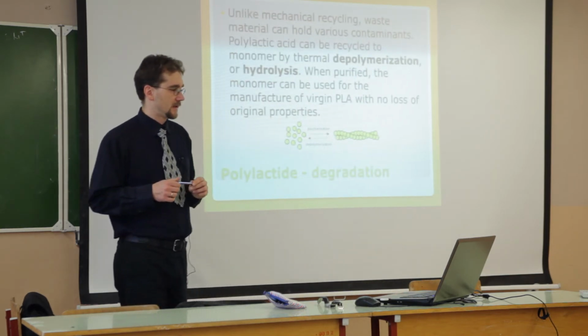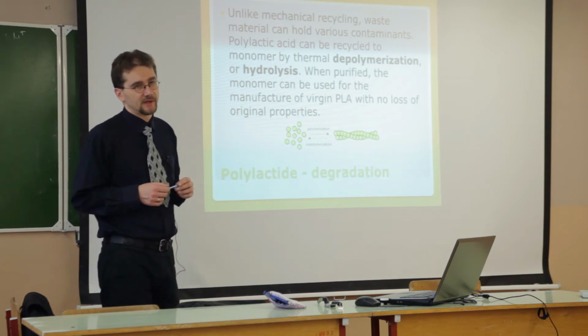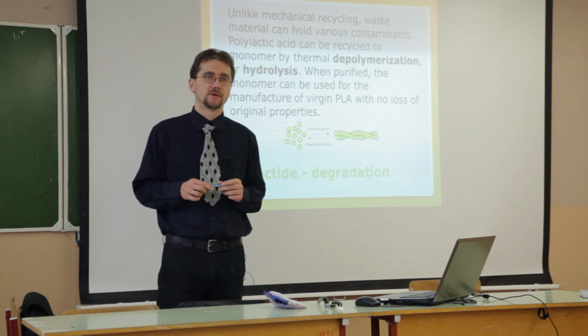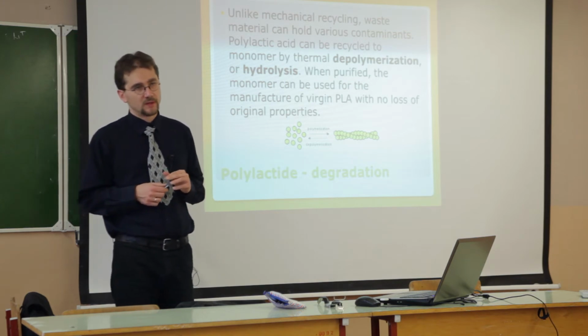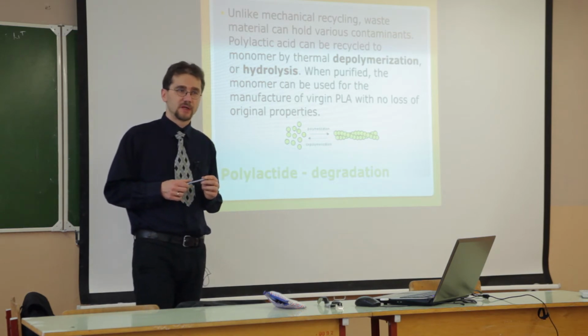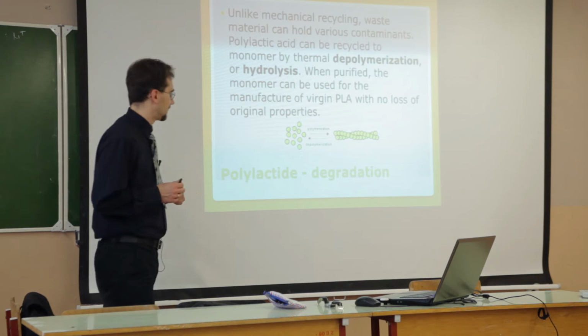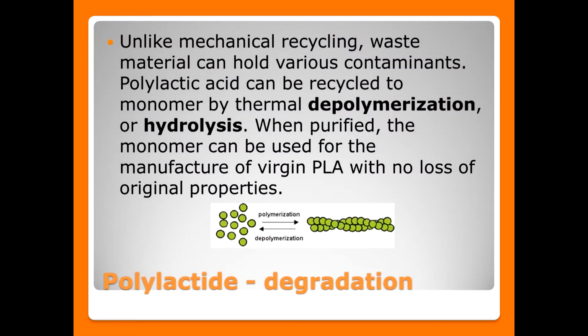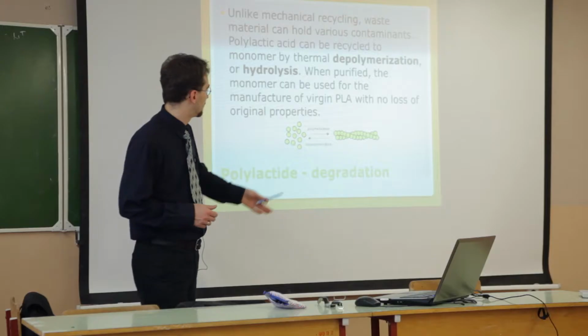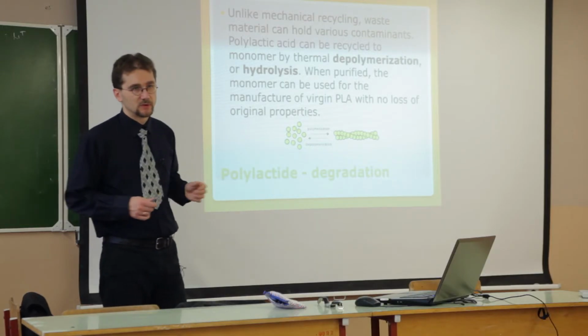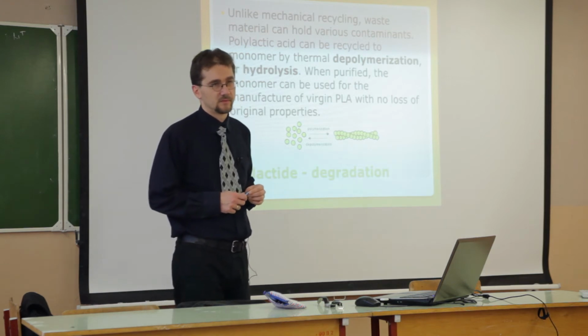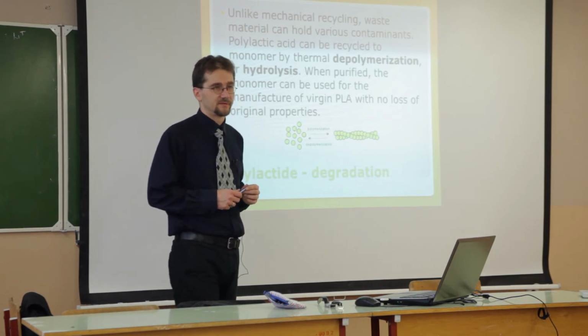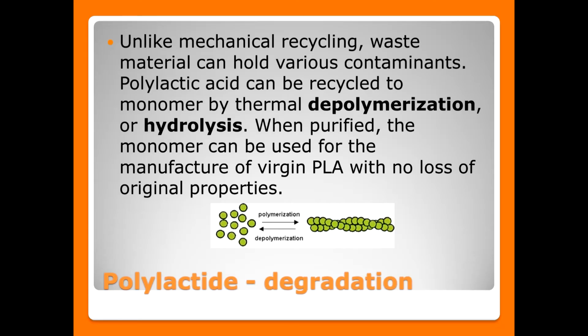It is important to have good quality polymer, because when there are no more additives and contaminations, it will degrade. The first step is depolymerization, and the degradation can mostly proceed very easily into the monomer again. The monomer is fully safe for use by humans.